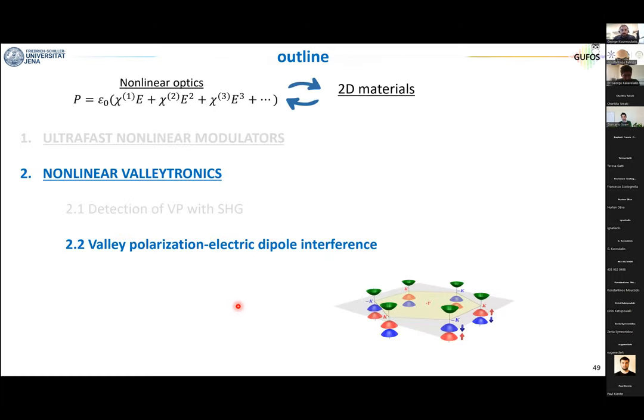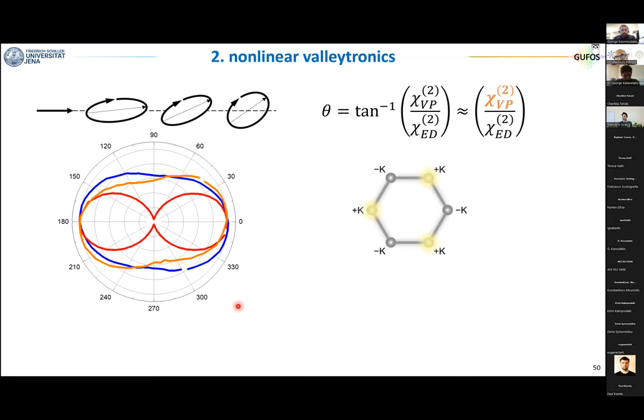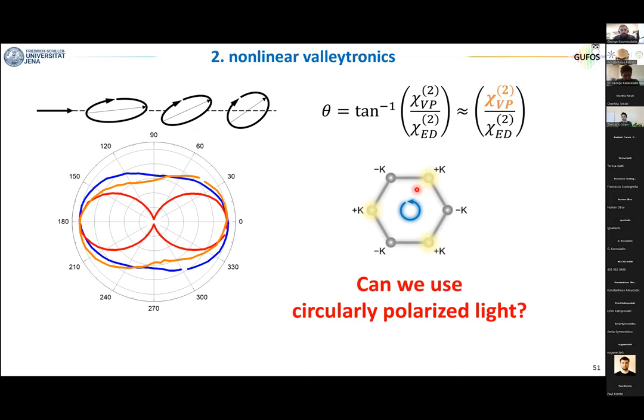And now this also tells us another thing that I will use for this valley polarization interference. It is the following. In the experiments that I showed until now, basically we have to shine elliptically polarized light because the circular component breaks time reversal symmetry and the linear component measures the rotation angle. However, this method is again not the ideal one because if we really wanted to selectively pump the valley, we should shine circularly polarized light on the sample. So the perfect excitation is when we shine circularly polarized light and we can be selectively on K or K prime. So the question is, can we use circularly polarized light to measure the valley polarization? With this method, certainly not, because the moment that we go circular, we cannot measure the rotation angle anymore. So we are lost.